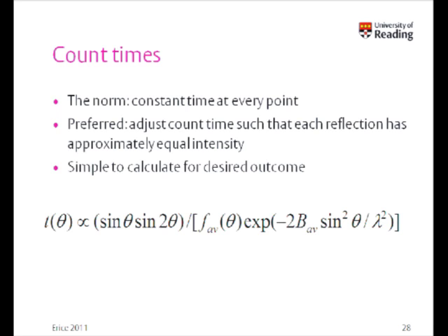What was most interesting, in fact, was that when we went back and reanalyzed some very old BM16 data from the ESRF, so just on the bending magnet, we actually found that the radiation damage was still there. We simply hadn't noticed it. It was much more subtle because of the relative lack of flux on the bending magnet.